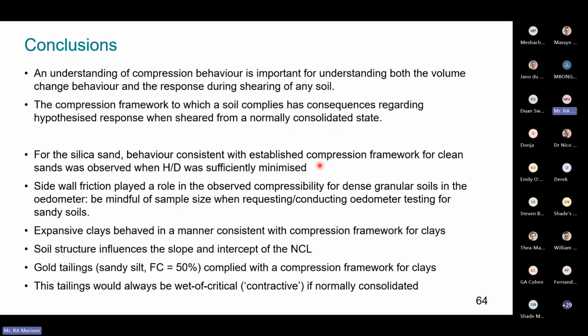And if we look at some more specific conclusions for the different soils, it is advised to minimize the H/D ratio when testing a granular material as far as practically possible. So specify the largest sample diameter that you can for your lab testing program. And then for the expansive clay, soil structure is an important factor to consider because it influences the slope and the intercept of your normal consolidation line. Finally, for the gold tailings that we considered, with fines content of 50%, this complied with a compression framework for clays. And what it means is that this tailings would always be wet of critical if it is normally consolidated.